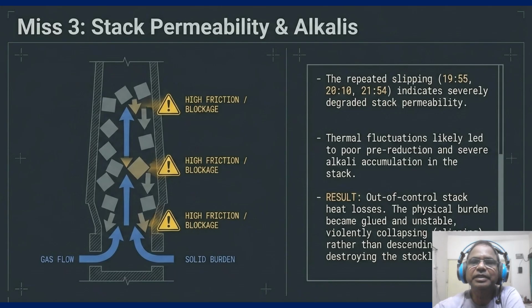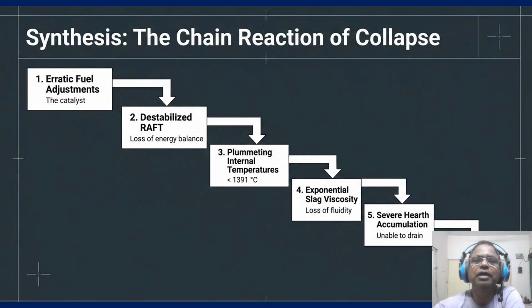So when we synthesize these three mistakes, we see a clear lethal chain reaction that led to system stress. So coming to the synthesis part. So here the chain reaction of collapse is shown. As you can see, it started with the erratic fuel adjustment, the catalyst. This led to a destabilized raft and a loss of energy balance. So step 3 is plummeting internal temperature below 1391. Step 4, an exponential spike in slag viscosity and a loss of fluidity.